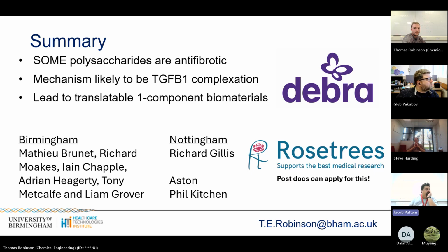And I think there's a third one, lambda carrageenan. It doesn't form a gel at all. So iota, I did make a point of saying it needs a boatload of calcium because it gels in the presence of calcium, but it also forms weak gels. And that's the problem when you're trying to microstructure them, because you can form it into a microstructure. I think I showed you it very nicely.